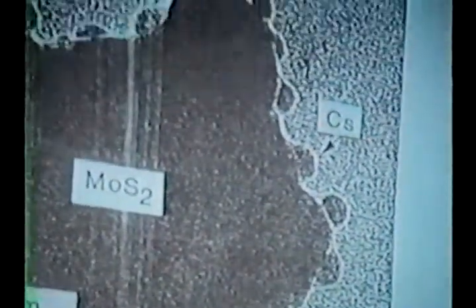Indeed, it is bifunctional because if one adds cesium to the molybdenum disulfide, one does promote this alcohol synthesis in the first place. If one looks at the disulfide catalyst doped with cesium at some intermediate concentration at which alcohols are produced at maximum, one sees this morphology.